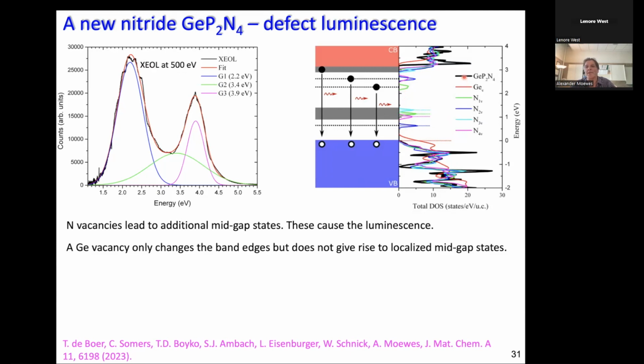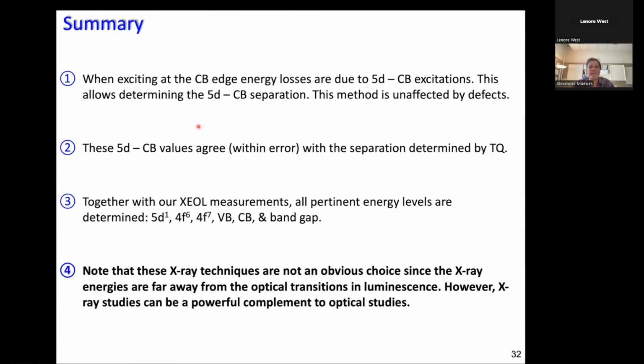When you look at the germanium, here we have calculated the same thing. When you take out a germanium atom, then the band edges are reshaped here. It's the red curve, but there are no additional states in the band gap. So the upshot of all of this is, with the help of our calculations, we were able to assign, here are now the fits, that this luminescence comes from intra-gap defect states. So you create a certain imperfection, and that leads to additional electronic states in the band gap. And this now gives rise to visible luminescence that would otherwise not be expected in a perfect crystal.